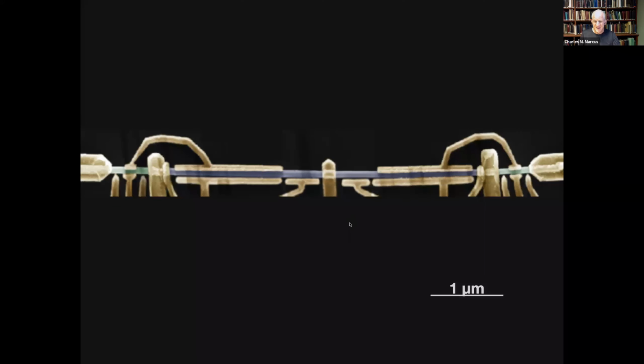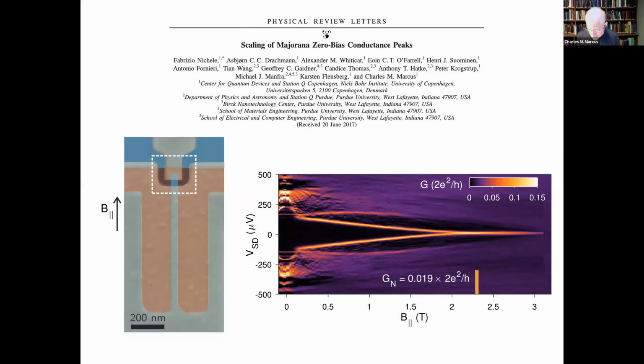It's working okay. What I wanted to say was that by now, these one-dimensional wires, which are grown out of III-V semiconductors, typically indium arsenide or indium antimonide, have become kind of an industry, and people are taking the topological states that have been identified through tunneling experiments and producing complex structures and applying dynamics and moving gates around. And although there's still some general anxiety about the ambiguity of the signatures of Majorana zero modes in these systems, the field has gotten pretty sophisticated based on these wires and gone a long way beyond the original set of ideas. Of particular importance, and you'll see why on the next slide, is the ability to scale these by reproducing a wire structure, not being grown nanowires, but rather by depleting a two-dimensional electron system.